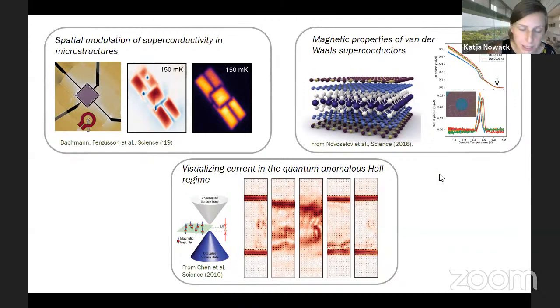There is a different scanning squid technique out there that was pioneered by Eli Zeldov, and he essentially has a squid that's fabricated on the tip of a quartz tube. And so these squids can get extremely small, I want to say tens of nanometers. And because you have this tip geometry, you can also get really close to the sample. In that technique, I'm not quite sure what the best spatial resolution in actual real images is to this point, but in principle you should be able to get to tens of nanometers spatial resolution. So you can push scanning squid towards that, but then you really have to work in a geometry where you can also get the squid close enough to your sample.